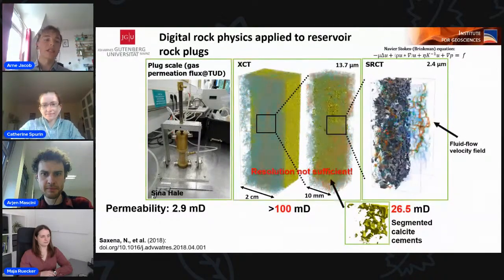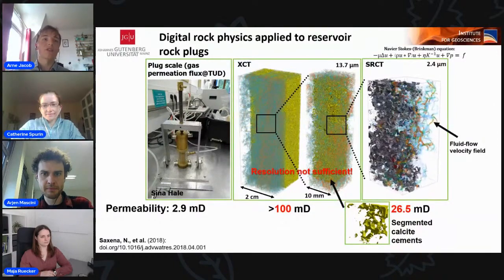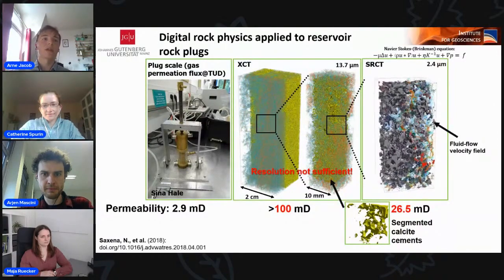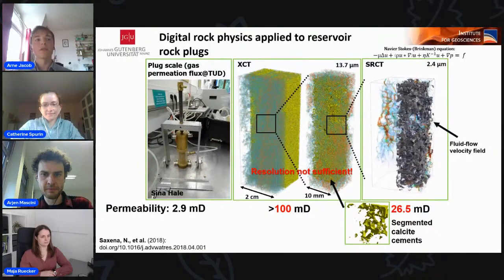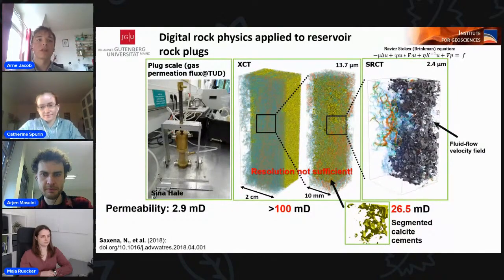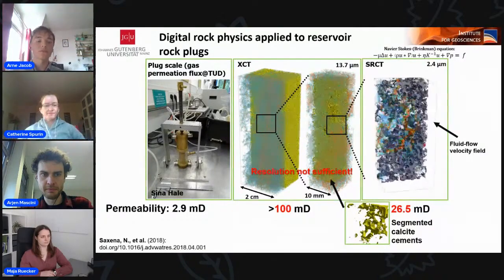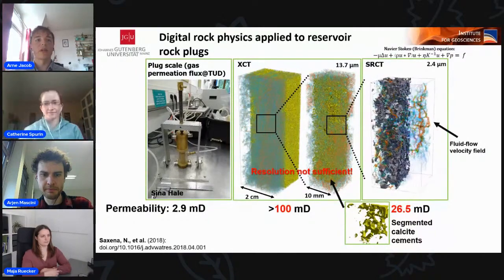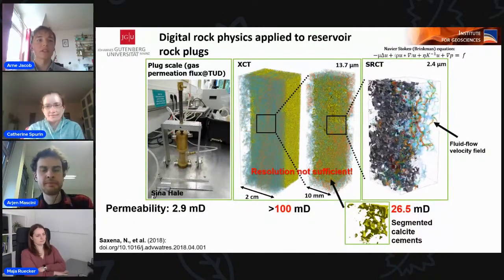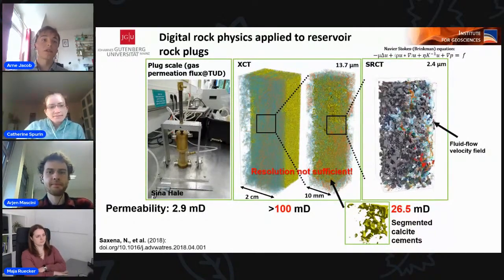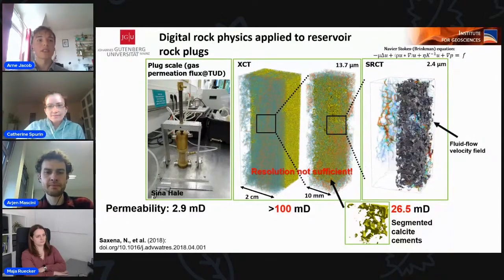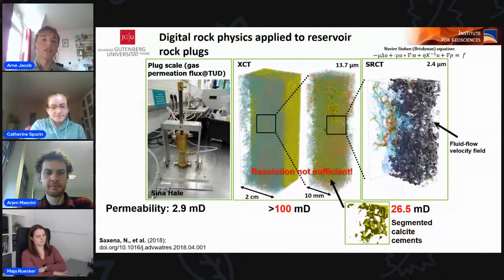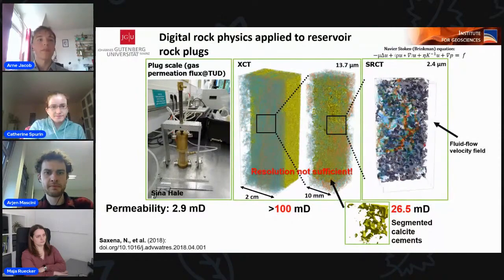The images on the right-hand side have a much better resolution of 1.2 micrometers, while we binned them with a factor of 2 before reconstruction to obtain a better signal-to-noise ratio. When you compare the permeability of the different methods, you can see that they differ a lot. In the larger plug samples, this is induced by the resolution, which is not sufficient for these types of rocks.